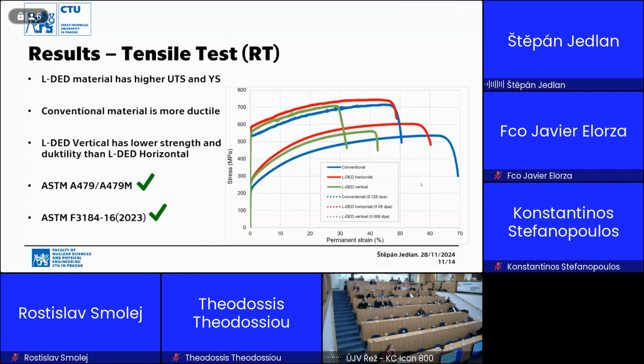Now for the tensile test, that is the most exciting one. As you can see, the first thing is that the radiation damage of each type of material is not the same, and that is mainly because of the axial distribution of neutron flux, which resulted in the conventional material being the most irradiated one. There is also the result of the radial distribution of neutron flux, as the conventional material shielded the horizontal 3D printed material. So as a result of those two things, the conventional material was the most irradiated, and however, we were still able to fulfill the standards for the non-irradiated material. And as you can see,